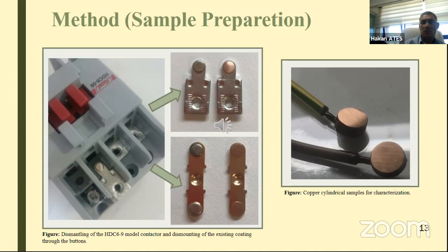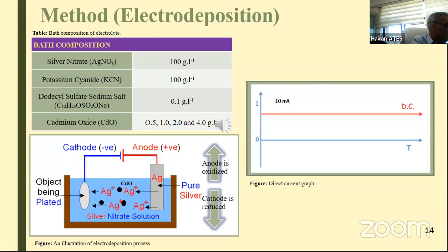After dismounting, cleaning with pure water and drying of the samples, the unwanted regions to deposit are painted with nail polish. Here on the table, our deposition bath components can be observed. Silver nitrate, potassium cyanide, sodium dodecyl sulfate, and cadmium oxide with different amounts are used. In the figure below, the electrode deposition setup is shown.